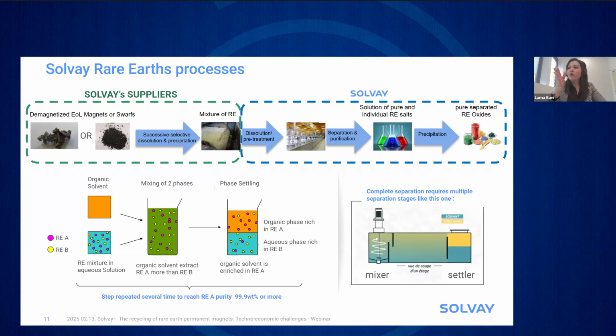The separation equipment is what you are seeing at the bottom right of the slide. Okay, you have what we call a mixer. At this part of the equipment, an organic solvent is mixed with an aqueous solution containing the mixture of rare earths that has been dissolved before entering the separation. Okay, so here we have all the rare earths together, and the solvent will have a specific affinity to one rare earth or to one group of rare earths. Okay. At the settler part, so the end of the equipment, the two phases, organic and aqueous, will be separated, and the rare earth that has been extracted by the solvent will be recovered in the organic phase.